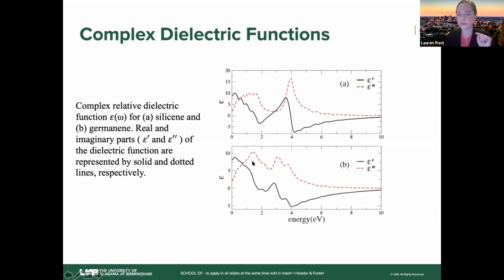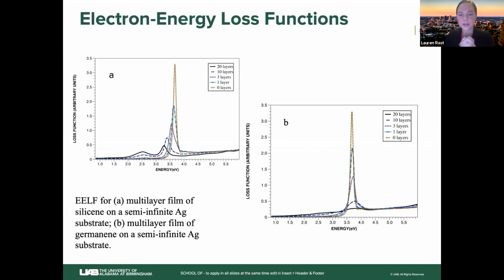So this is just the calculation for the dielectric function of silicene and germanene. In these spectra, we get a marked difference, with broadening of the peaks, with 3 layers or more. So this could help in experimentally verifying that you have only a few layers of these materials on top of a metallic substrate in experimental conditions.